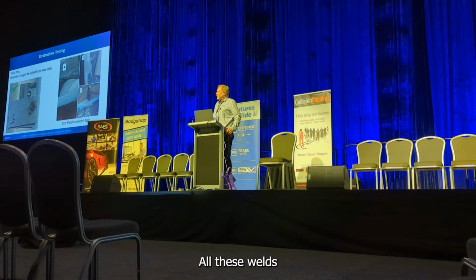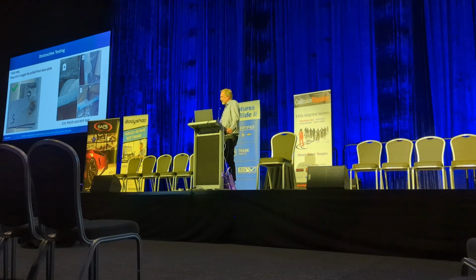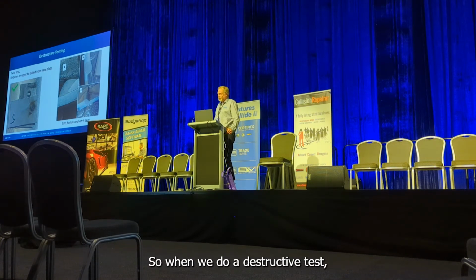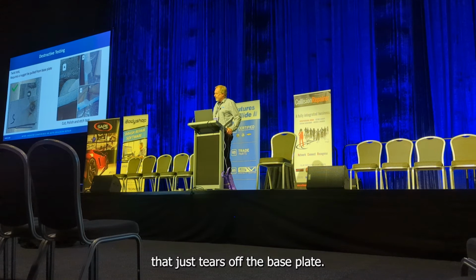All these welds visually look superb. That's the cut, polish and etch method. Sample A, you can see the weld itself comes out a different colour when we etch it, and that's just sitting on top. So when we do a destructive test, that just tears off the base plate.